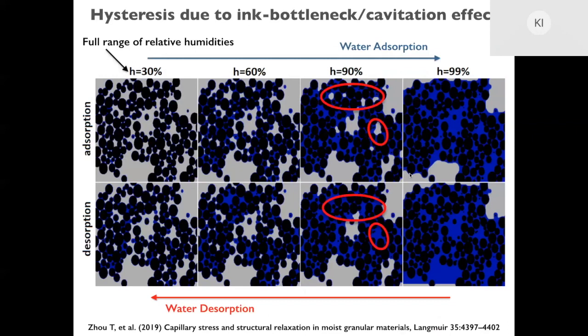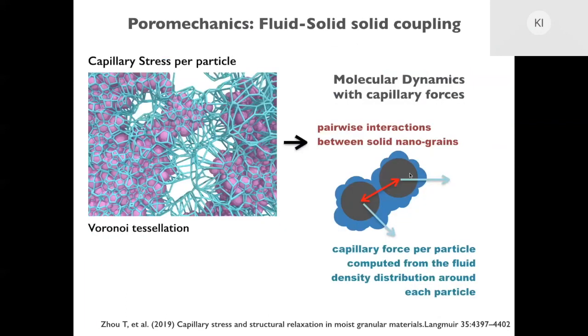And you can see that usually when people do adsorption and desorption of water in cement, they observe a hysteresis. And the reason for this hysteresis is this ink bottle cavitation effect that you are seeing in red. So basically, the material takes much more time to desorb the amount of water. So the next step in this simulation was that once we know the distribution of water around the grains, we want to get the poromechanical effect. We want to couple the fluid with the solid. And we did this by computing the capillary stress per particle. To do so, we had to do the Voronoi tessellation.